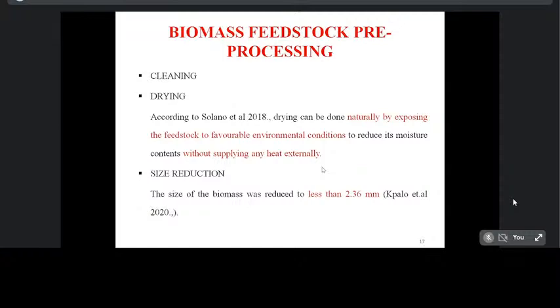The next step is size reduction. The biomass was reduced to less than 2.36 mm. As per Kpalo et al. 2020, size reduction is one of the very important processes prior to biomass briquetting. Size reduction also increases the bulk density. The size can vary up to a maximum of 80 mm according to UNEP 2011, but here I am taking 2.36 mm, because the smaller the size of the collected agro-waste material, the higher the density.